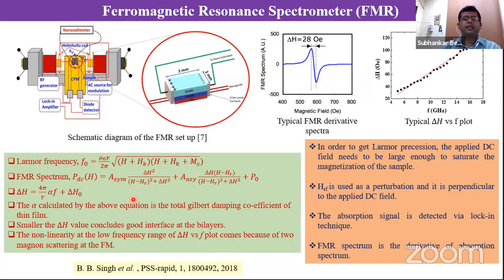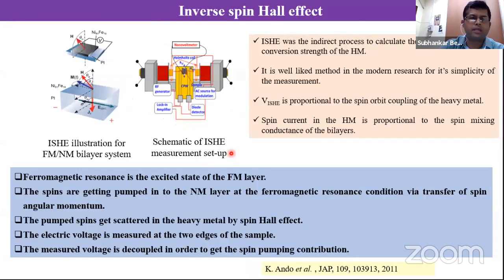So this is basically the schematic of our ferromagnetic resonance spectrometer in our lab. It is a CPW, so a coplanar waveguide based system. You mount the sample in a flip chip manner, so the top surface faces the CPW. You excite with an RF field. There is a Helmholtz field by which you measure this FMR spectra as a function of magnetic field. Then you will have a resonance. You can use the Kittel equations, and then you can extract the damping parameter, line width, and so on.